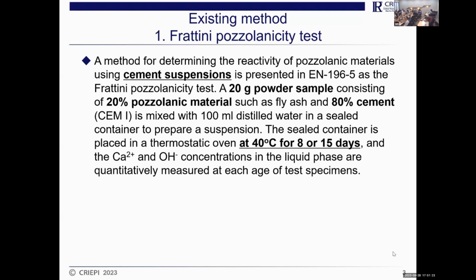And there are already a few testing methods. Firstly, it's named the Pozzolanic activity test. It also uses cement suspensions, and the suspension is made from 20 grams of powder samples, and 20% is pozzolan-like material like fly ash, and the other 80% is cement. And the reacting condition is like this, 40 centigrade, and keeping it for 15 days.